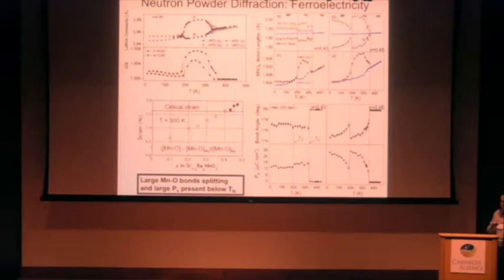We have all measurements for these bond lengths, and then the dominant effect from which we can estimate polarization—spontaneous polarization is very large—comes from the bond angle in-plane. The bonds are basically adding up to the average, but because they are out of the plane, you see the angle in neutron diffraction experiments. So bond splitting is still present—you see the effect at antiferromagnetic transition temperature, but materials remain ferroelectric below this transition.